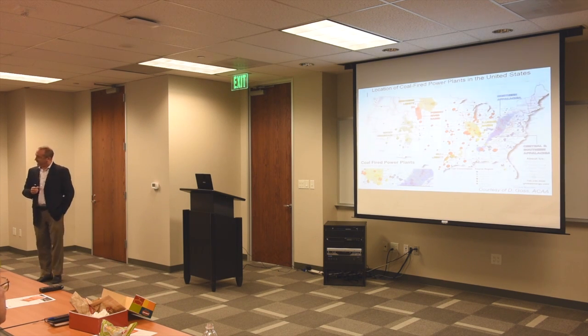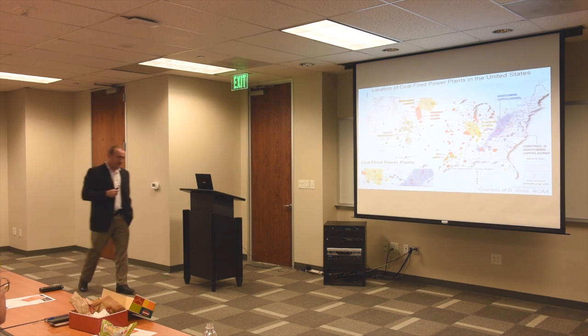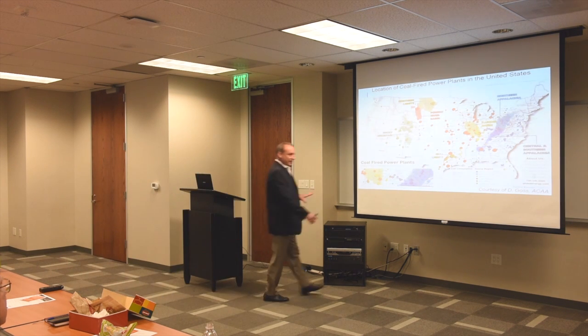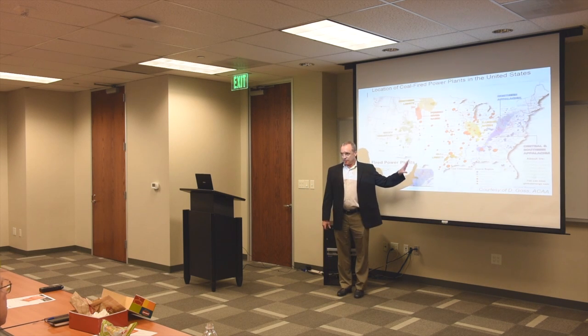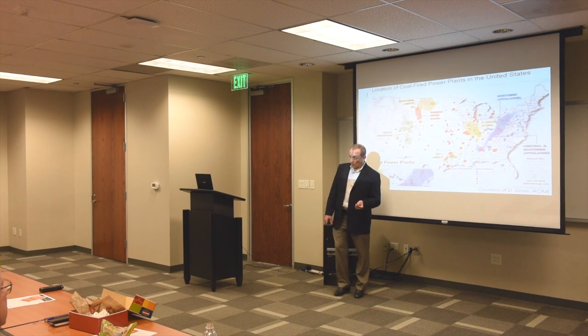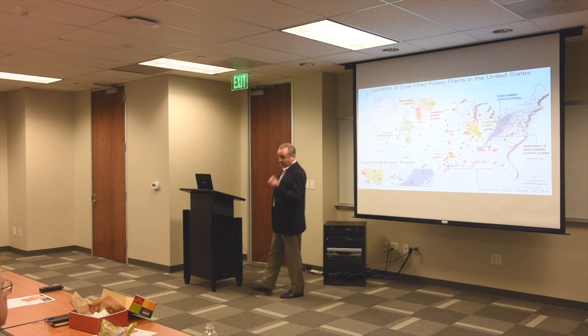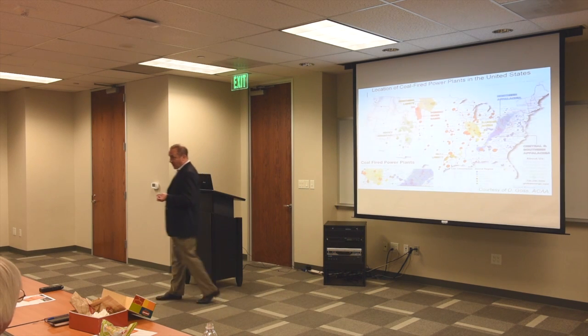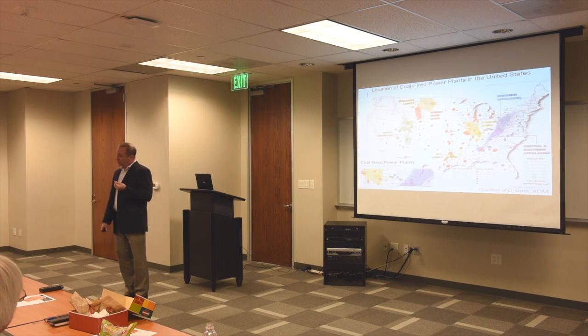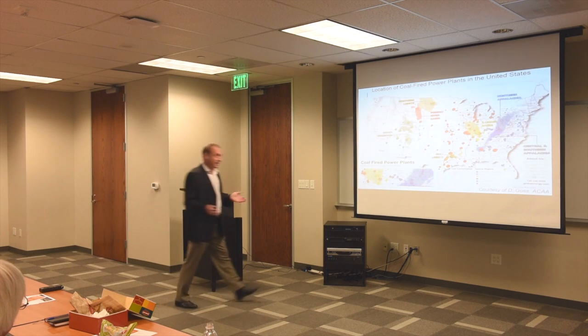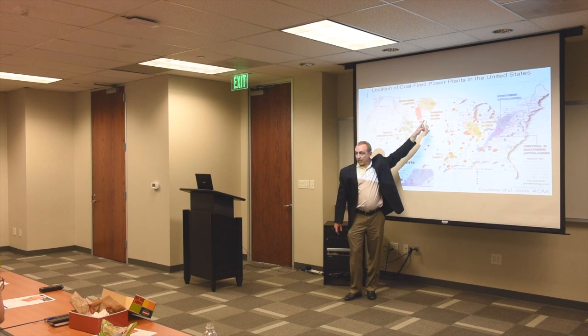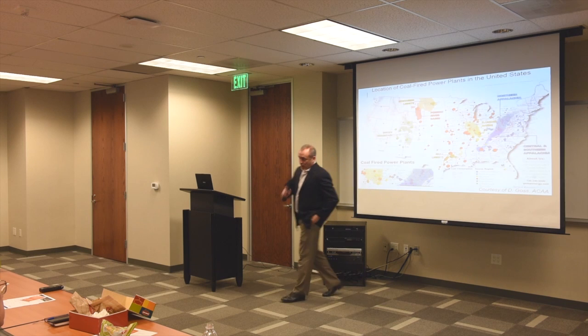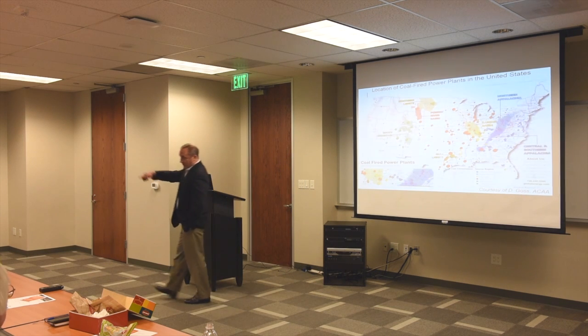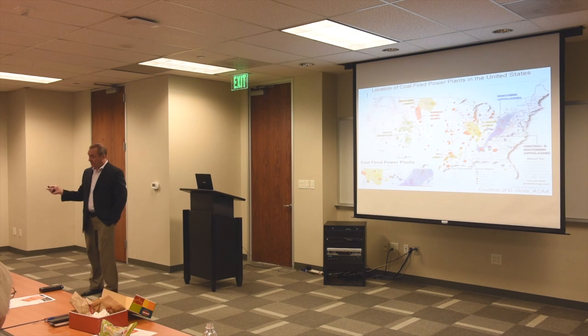This is a map of the United States showing coal-burning power plants. The only point I want to make is that in the last 10 years, we've moved towards a different coal source in Texas and elsewhere to reduce emissions out of power plants. Right now about 2/3 of the power plants in the US are getting their coal all the way from Wyoming, Powder River Basin. And when that happens, as soon as you change your fuel at your power plant to meet this emission standard, all of a sudden your fly ash changes drastically overnight.